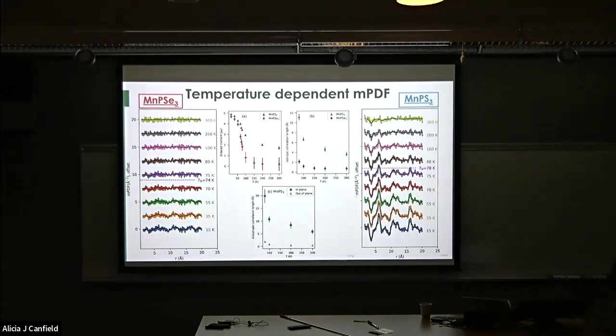So this was all at the same temperature, but shouldn't you have better contrast in some sense if you take advantage of the fact that magnetic order goes away or becomes extremely short range at high temperature? So this is the temperature series, sorry, where we started down at 15 Kelvin. For MnPSe3 here, you can see the scattering, this is just the pure magnetic scattering now. This is the residual, what's left over after we do the atomic fit. The MnPSe3 is weaker, even at 15 Kelvin, and as you go through the transition, maybe there's still some magnetic scattering left, but it dies off pretty quickly. For MnPS3, you can see the scattering is much stronger, and it persists all the way up to room temperature.